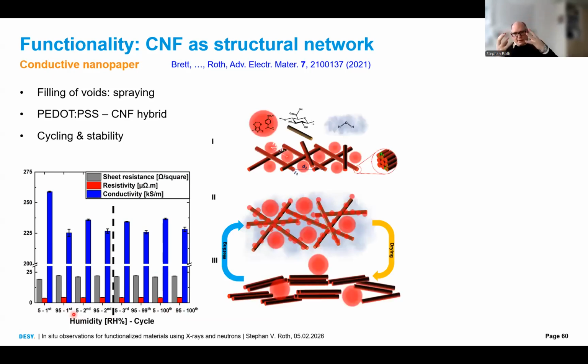We know the structure of our CNF template is individual fibrils bundled into agglomerates and voids. And the voids are filled when we imbibe the PEDOT:PSS in water. With this solvent, the water solvent evaporates, and the PEDOT:PSS is left as spherical aggregates. And it also coats the CNF. This is known via AFM measurements from a group at Linköping University close to Stockholm. So we start with this drying.